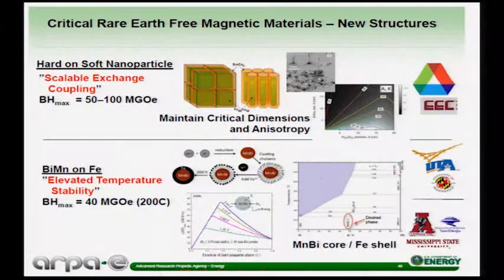So we're trying to figure out better designs. One idea that is working, at least at lab scale and small scale, is you have a mixture of the good permanent magnet surrounded by a soft magnet, but on a mesoscale, so that the permanent magnet induces the magnetism of the soft magnet. So it's a larger volume permanent magnet, and still has the coercivity and its permanence in terms of magnetic field stability. So that's one approach of what we call scalable exchange coupling, to mesoscale instead of an atomic scale.